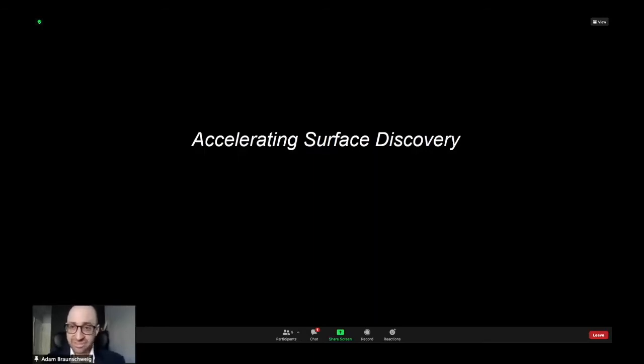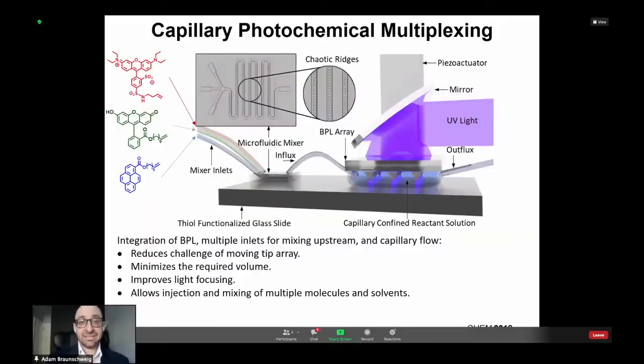So what we did is we stepped back and we spent some time developing new tools for accelerating discovery on surfaces. The first one I want to tell you about is this system that couples these massively parallel tip arrays with the ability to introduce new inks underneath the tips and change the reaction conditions within a single experiment. And by doing that, what you can do is in a single print, try tens or hundreds of different conditions, and then what would take, using current tools, weeks or months, ideally do that work in a single afternoon.